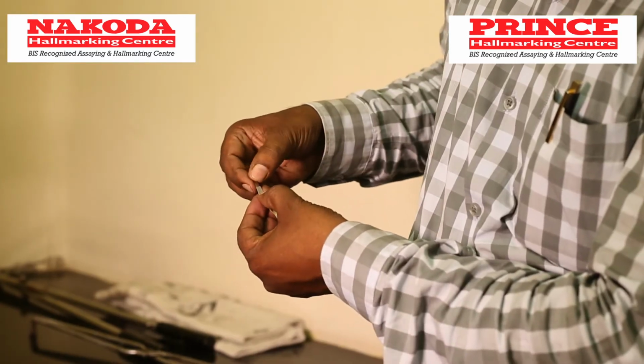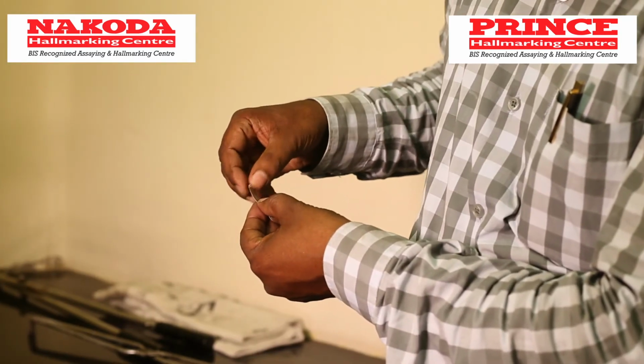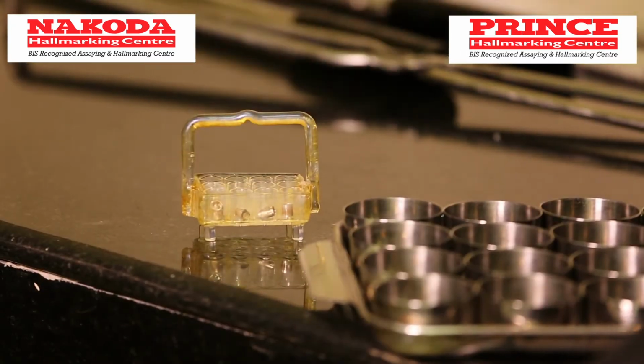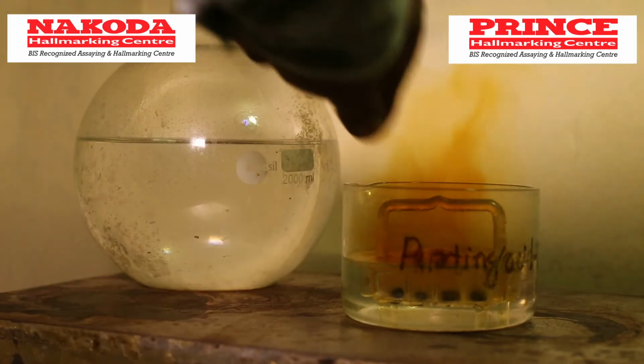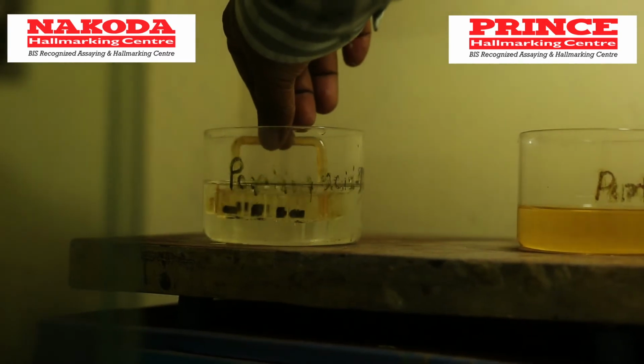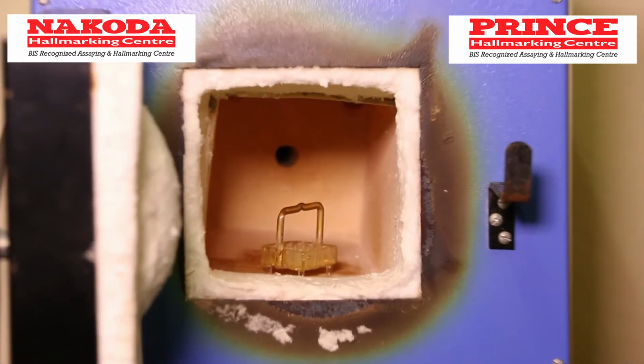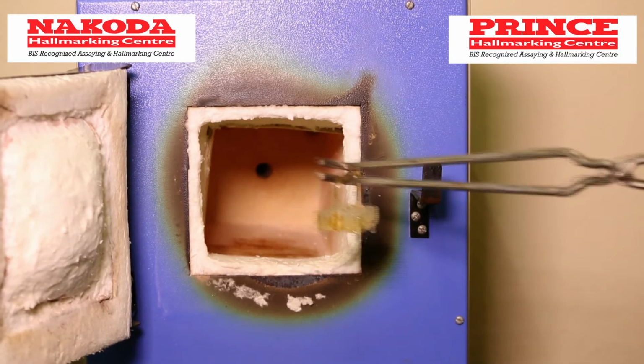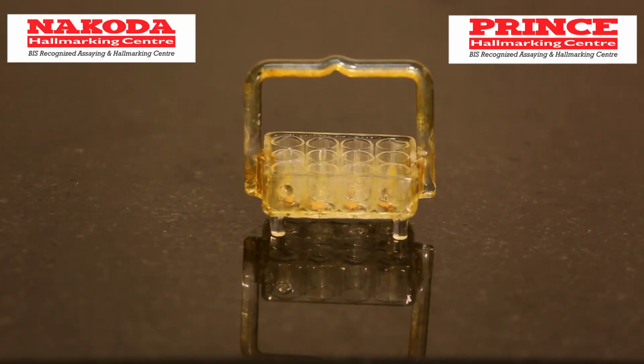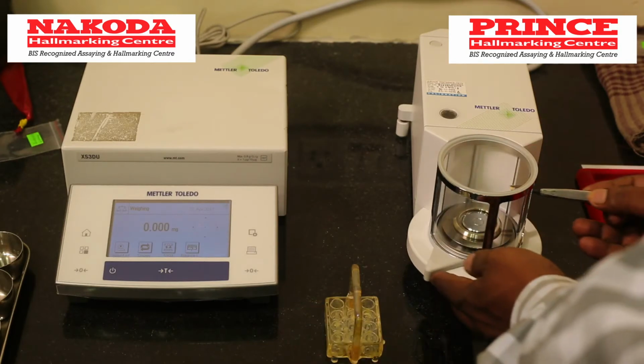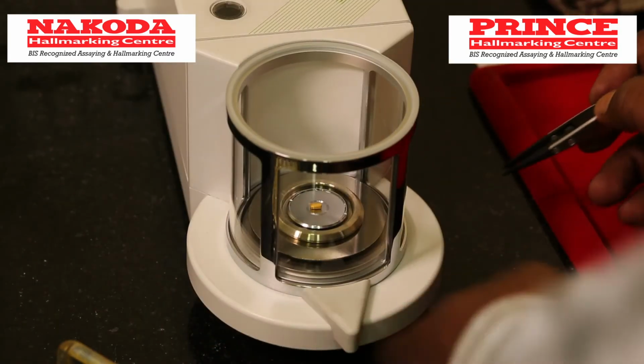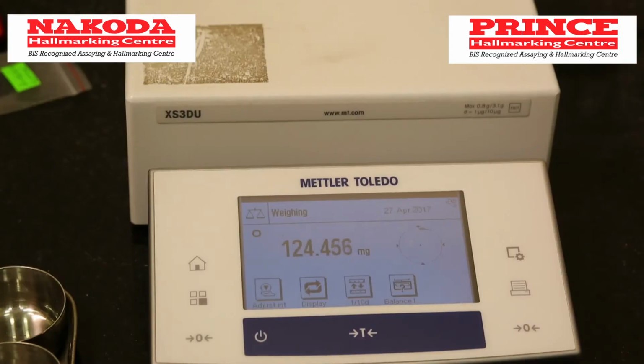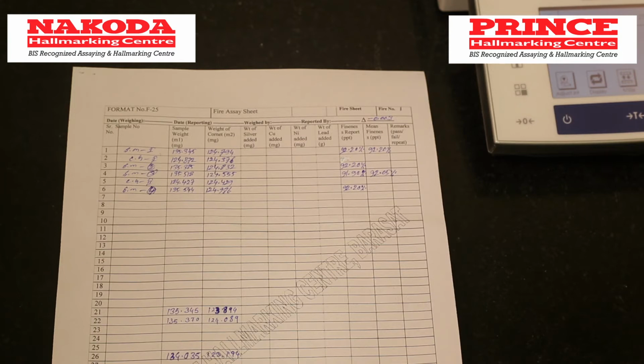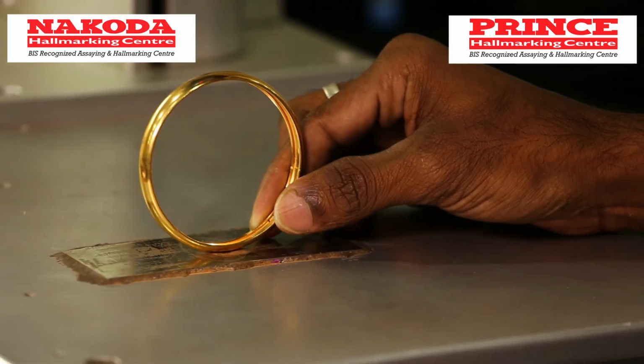After numbering, they are rolled by hand to form loose rolls and put into quartz trays for dipping in acid for removing silver. After washing, they are again heated in furnace and are taken out for weighing once they cool down to room temperature. Purity of gold, which is known as fineness, is determined from the difference in initial weight and the final weight of the sample. Lots that pass are hallmarked by laser marker.